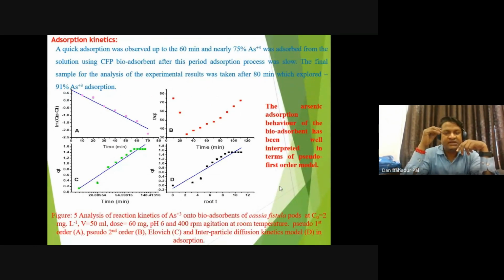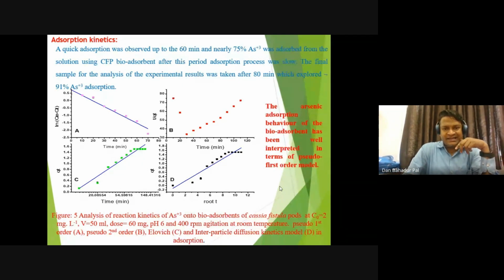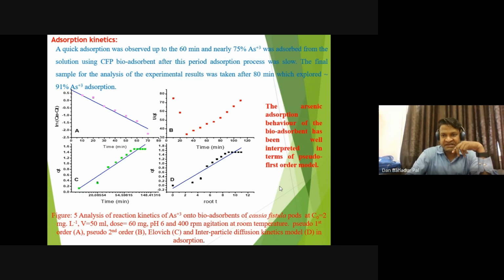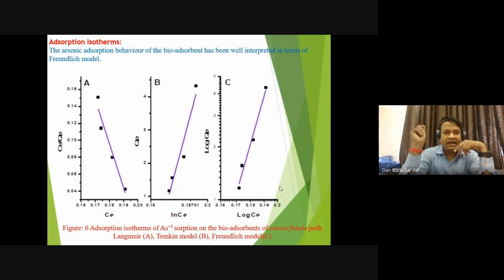Then we look at the mechanism, the adsorption kinetics. We generally take three or four components: concentration, different pH, and different adsorption dose. In all experiments, around 60 minutes gave 75% adsorption of arsenic, but after 80 minutes it increased up to 91%. For adsorption kinetics, we checked first order and second order kinetics, also Elovich and interparticle diffusion, but the best fit here is the pseudo first order in the arsenic 3 removal.